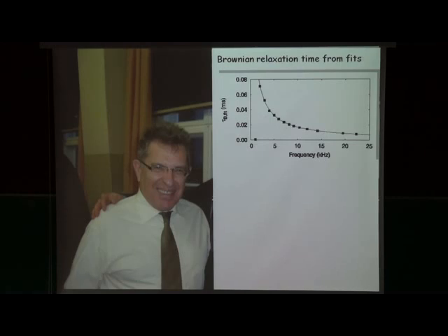Well, here it is. You see, this is the Brownian relaxation time as a function of the frequency, which were extracted from this fit. I told you that the Brownian relaxation time is completely determined by the viscosity eta zero, the hydrodynamic volume, and kBT. So it's purely geometric. It should not depend on the frequency. So this is really mind-boggling. It should be constant. It should really not depend on the frequency.